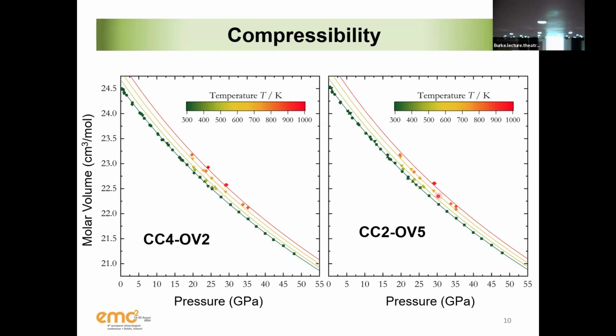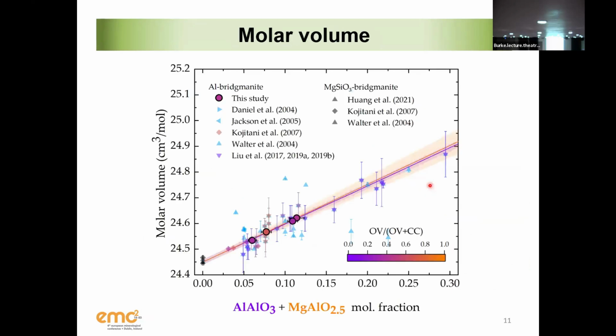The population of data at high temperature is not that large, but you can imagine that once we reach that kind of hole, then either we stop the experiment or we break the diamond. And this always depends on how much money you have. I normally try, even at BGI, to stop the experiment. That's why we don't have so many high-temperature data, especially not at very high temperature, but they were enough to constrain all the EOS parameters of a Mie-Grüneisen equation of state with a Debye approximation, which are these lines. So once I have that, let's look at the real data.